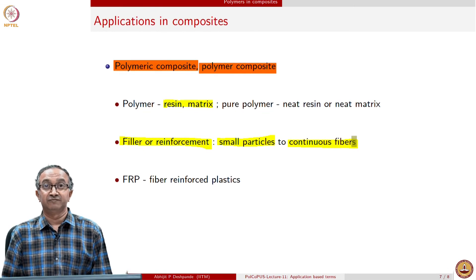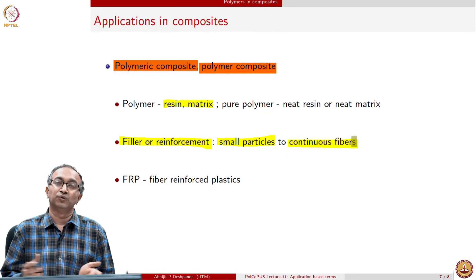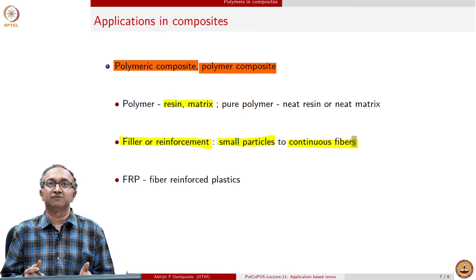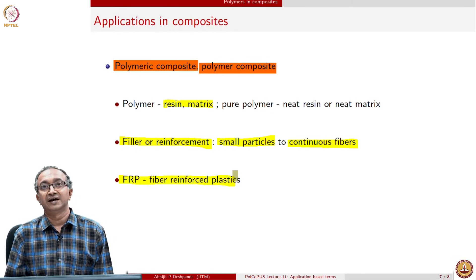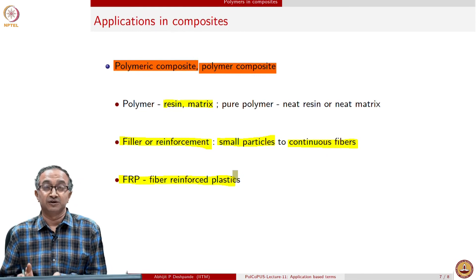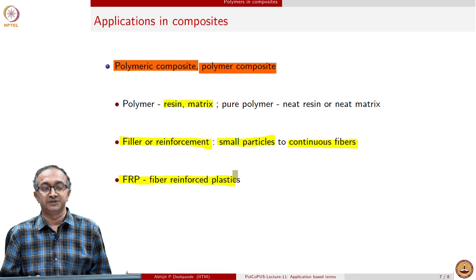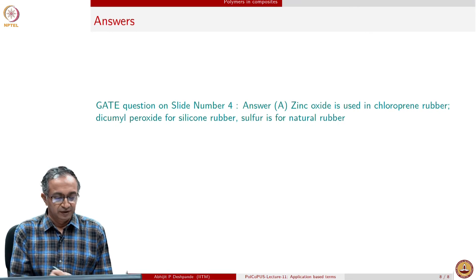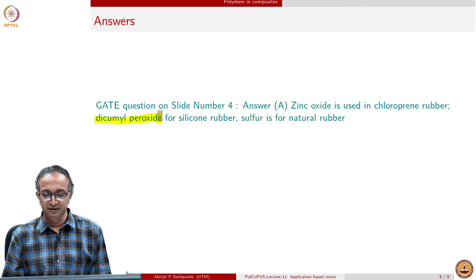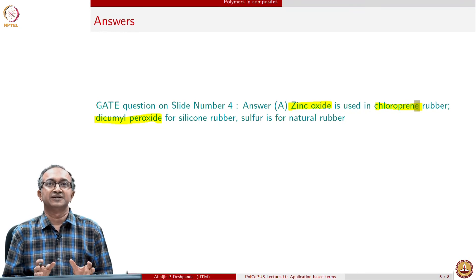Reinforcement is most effective when it is a continuous fiber — a very long fiber. In aerospace, when an aircraft wing is made, continuous fiber can run through the entire wing, which is meters in length, giving maximum mechanical property advantage. This is described by the term fiber reinforced plastic (FRP), implying thermosets or thermoplastics reinforced with continuous or other fibers to improve mechanical properties. Returning to the curing question: for silicone rubber, an activated peroxide material is used; zinc oxide is used for chloroprene; and you can now justify why an amine can be used for acrylics to complete the answer.